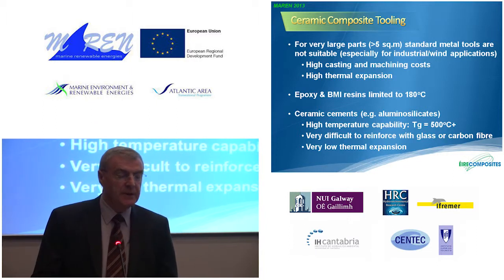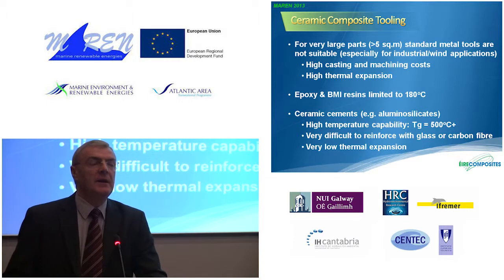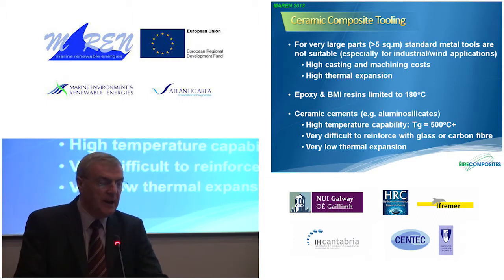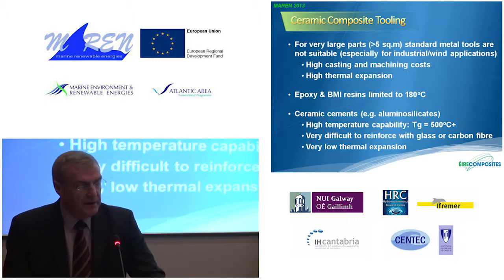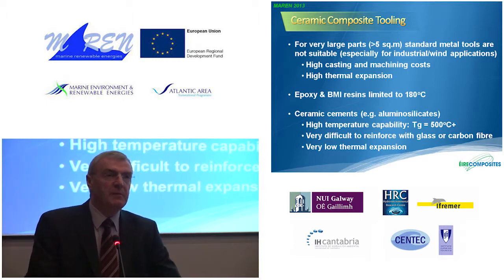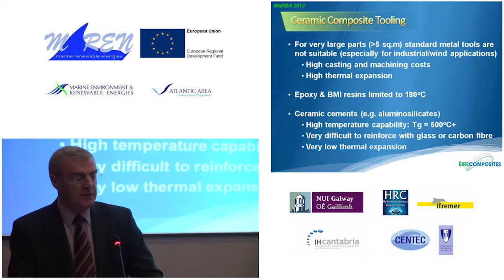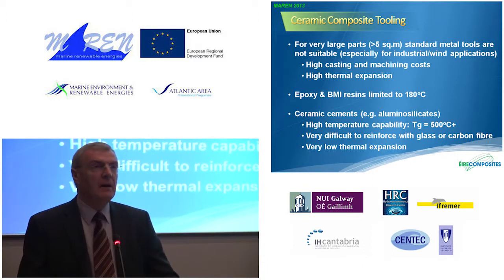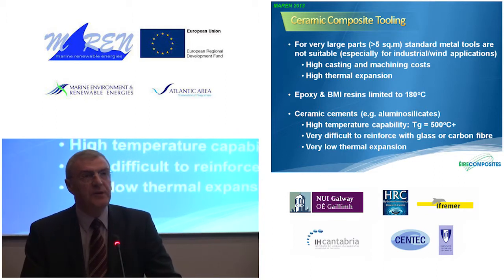The problem with the high thermal expansion of the metal caused stresses to be built up in the parts, and when you remove it from the mould, they tend to warp, and obviously the manufacturing of products that require accurate dimensions becomes a problem. The alternative material we looked at was epoxies and BMIs. However, the material that we use for making the hulls required to be processed at 200 degrees or so. The materials such as epoxies and BMIs, which are currently used to make tooling for the composite industry, however, would only really be useful up to about 180 degrees.